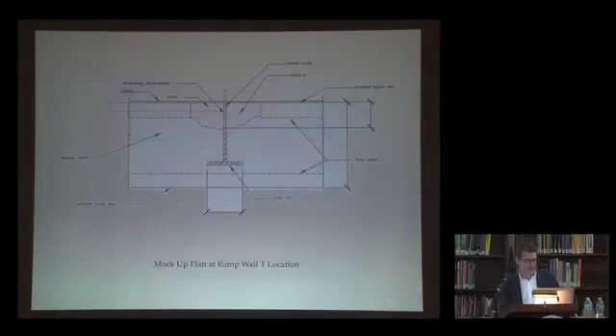This condition was viewed in different light forms, including raking light, as we were trying to prevent the joint filler from becoming concave or convex, depending on if the size of the joint was smaller or wider based on temperature. All of this was done so that the surface would appear smooth, uninterrupted, and organic as Wright had intended it.